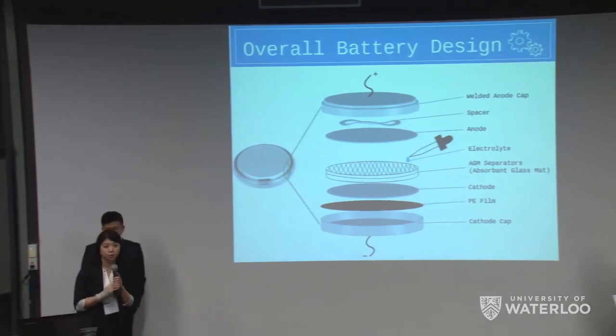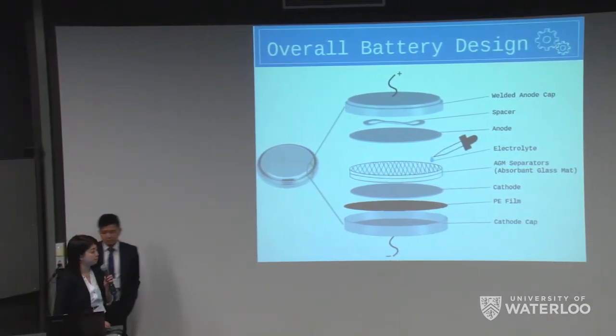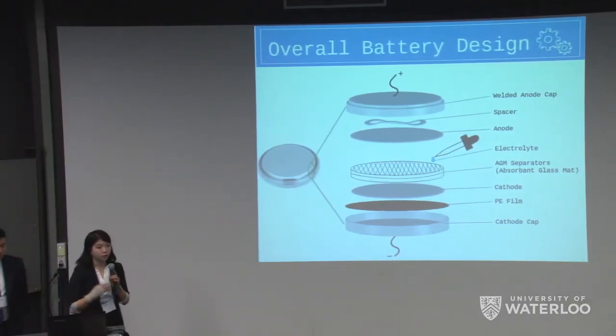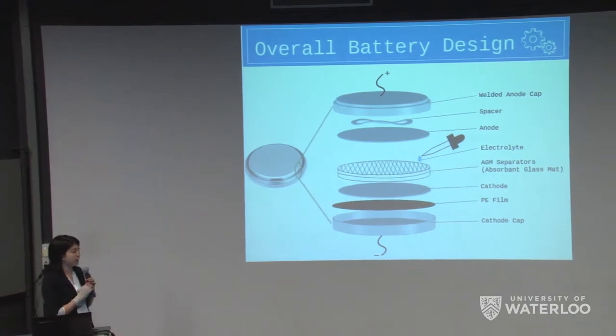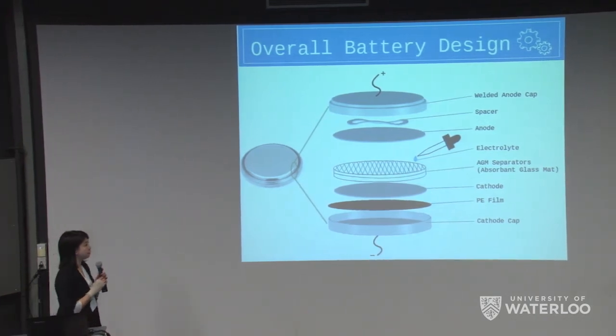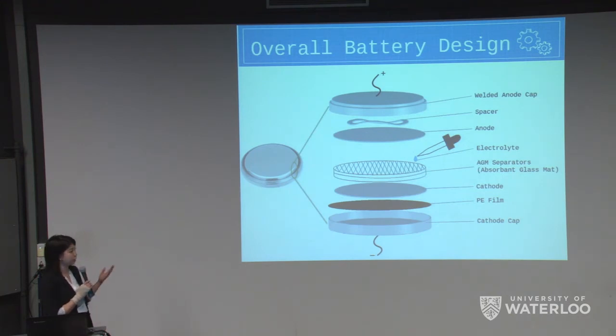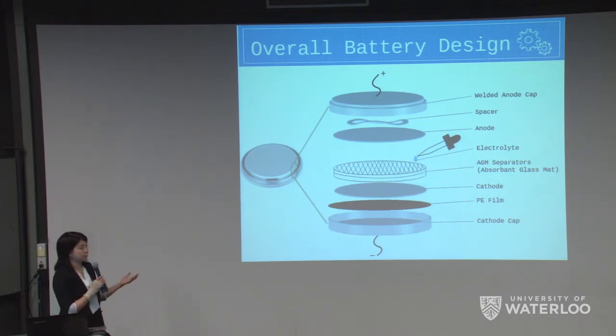So once we were able to optimize the gelling time for our electrolyte, we then had to test to see how it would work in a battery setting. And the easiest method of testing liquid electrolytes in battery settings would be to place the electrolyte in a coin cell battery. And this is because the casing and the fabrication process allows it to be a very tight and closed casing that doesn't allow leakage of the electrolyte to the outside of the system.